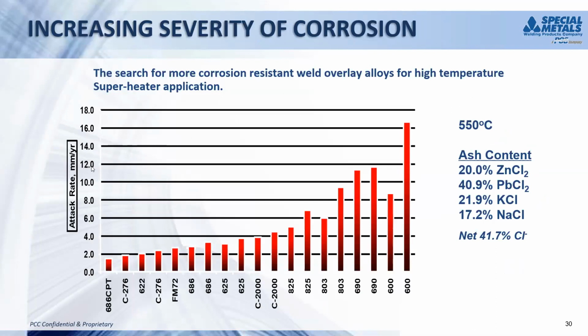In addition, in an effort to look at some new alloys, they created that experiment and ran tests with a wide variety of nickel-based alloys. You can see corrosion rates anywhere from substantially high attack down to the newer filler metals such as the 686 CPT with incredibly low attack rates. This is just a very good illustration of some different corrosion rates and different alloys that have been used on the superheater locations.